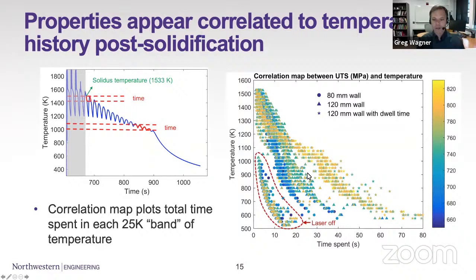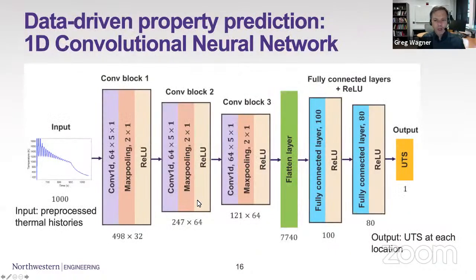And we could speculate about whether there is a phase change or some kind of precipitation that's happening in that region that's being caused by the amount of time at that temperature regime. But in order to actually take a temperature history and do more than wave our hands at it and try to see what's going on, we wanted to do something a little bit more quantitative with this. So we took these temperature histories and fed them through a neural network. And in this case, a 1D convolutional neural network, or CNN. What a CNN is good at is picking out these hidden features that might not be obvious, or at least be hard to describe quantitatively in some other way.